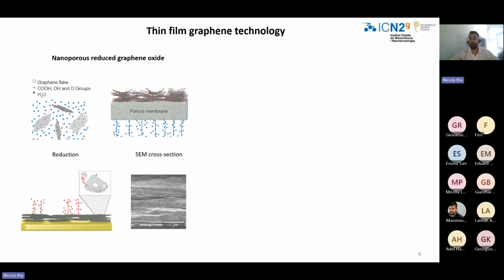So, in order to overcome all these limitations, in my group, we are exploring the use of a new material, which is nanoporous reduced graphene oxide, on a flexible substrate that is a polymer called polyimide. This material is produced by filtrating a solution with dispersed graphene oxide flakes to create a thin membrane, which is then hydrothermally reduced to create basal plane defects and oxygen vacancies. This creates a porous structure, which confers to the material special properties that I will describe later.